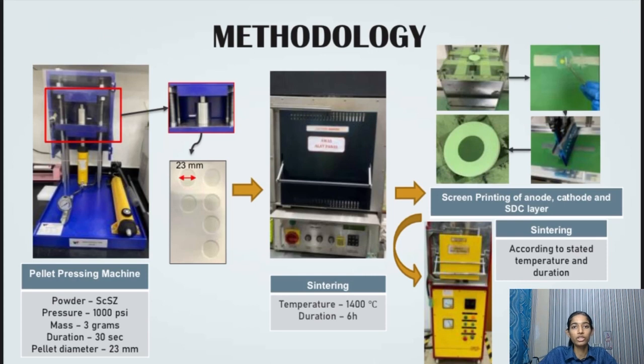So the methodology first starts off by pellet pressing of scandia stabilized zirconia powder into button pellet shapes. These pellets are then sintered at a temperature of 1400 degrees Celsius for a duration of 6 hours. Once the pellet has been sintered, it goes through a screen printing process, where anode, cathode, and buffer layer is screen printed onto the pellets. Once the pellet has been screen printed, it goes through the sintering process again.